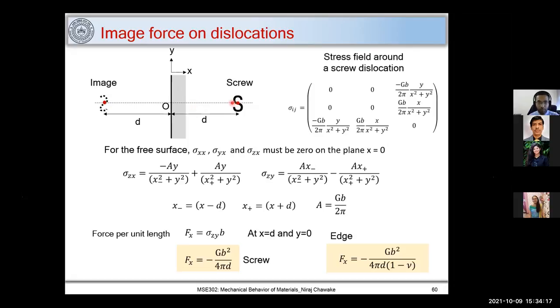So this may happen when you focus your beam on your sample, or you increase the intensity of the beam on your sample. So this kind of force can be understood using another dislocation which is opposite of this surface, and that is called the image force. I'm not going into details of it, but remember these formulas and try to find out what is the image force acting on your sample.